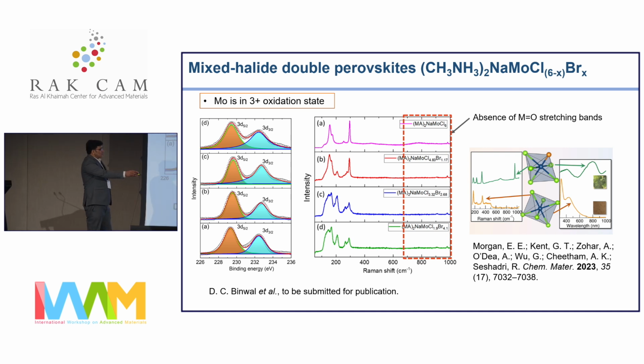And this was clearly analyzed in a recent paper from Tony's group, where it suggests that it's very, very difficult to control oxidation of molybdenum. But that is in 4+, and it goes to higher oxidation states, and it is hard to control that. But in this structure, the 3+ in a one-dimensional setting, we can precisely control this. It does not oxidize to any higher oxidation state, even under ambient condition, for some days.